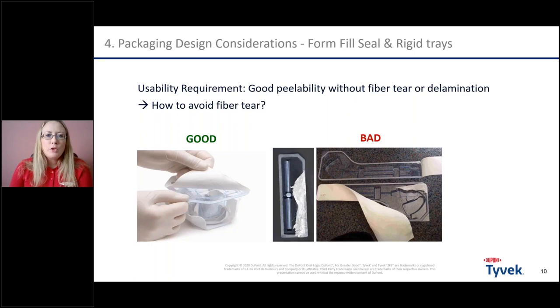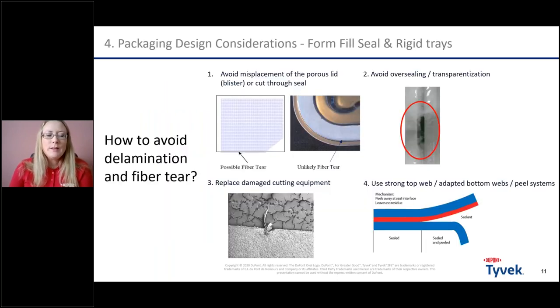Then in terms of trays, so either rigid trays, often form-fill-seal, rigid or semi-rigid or flexible trays. Also here, it's very important in terms of usability that we have a good peelability without fiber tear or delamination. So you can see here on the right side an example of a bad peelability, fiber tear, delamination example, which should not be the case. And here are some recommendations how that can be avoided or the risk be reduced.